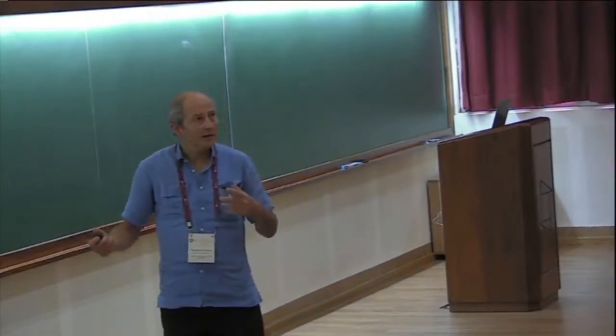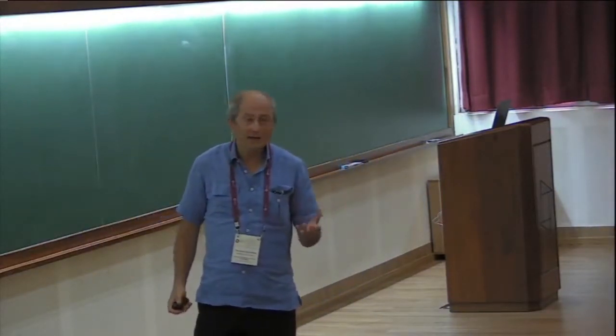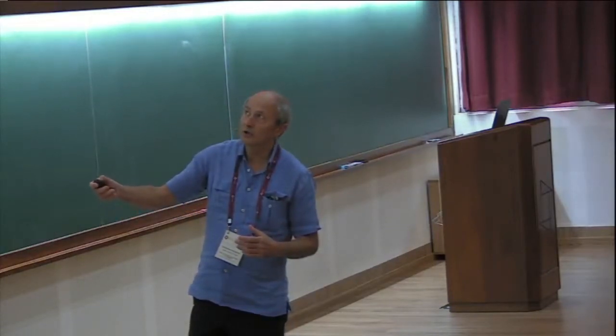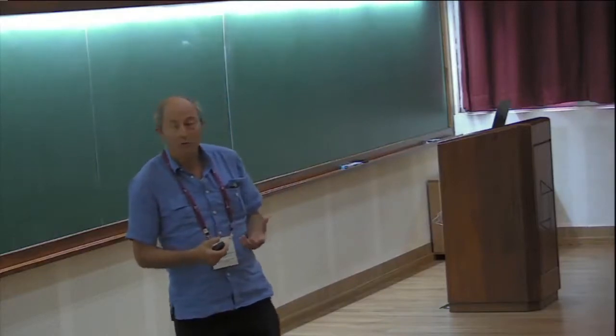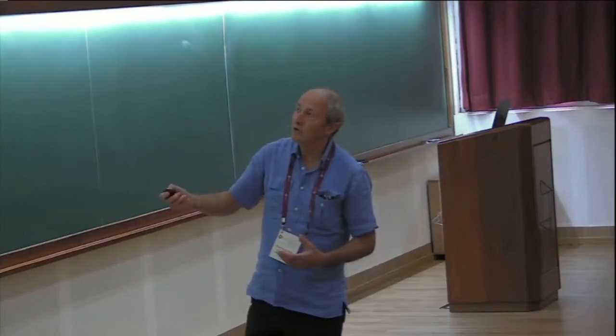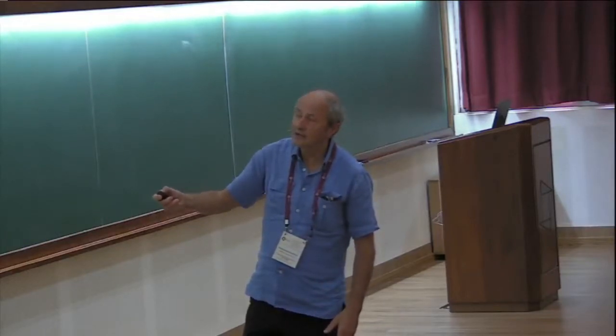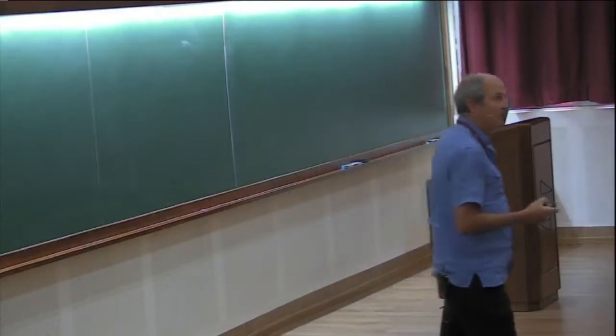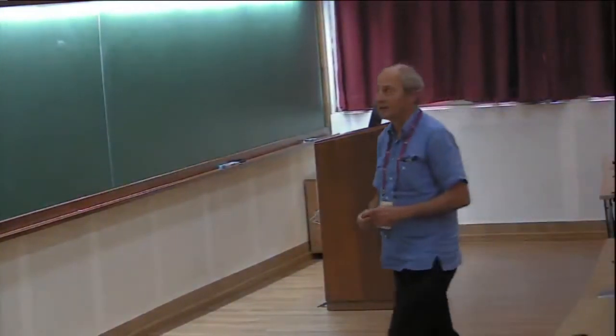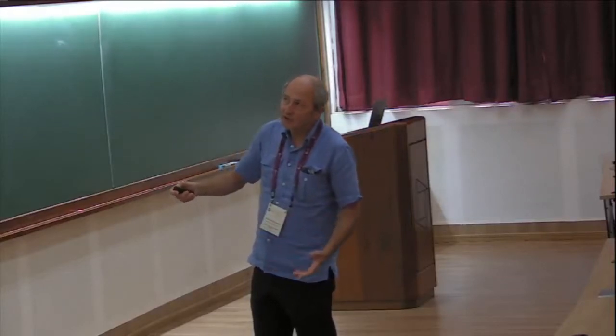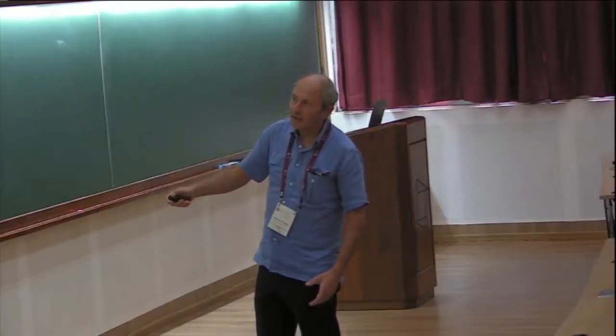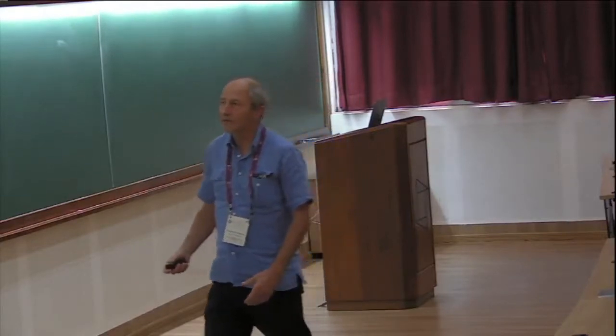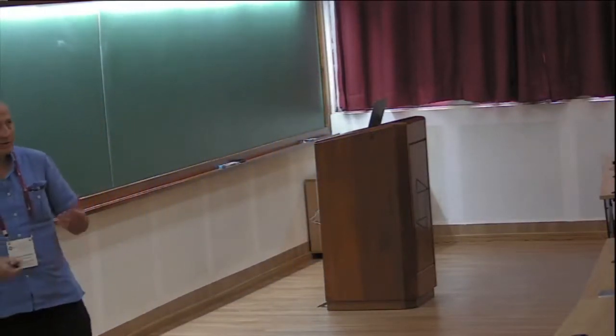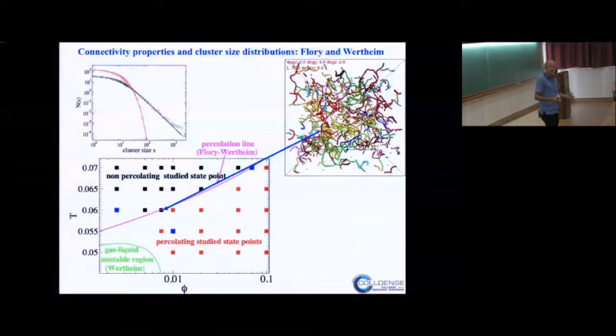We have introduced in the previous lecture the Flory-Stockmayer clusters. And those are the lines that you see shown here, compared with the simulation. You see how good the agreement is, even close to the percolation transition. So they're really a nice description of those clusters, based on the theory that we have discussed, that maximizes the number of different cluster types. So the system is essentially composed of a non-percolating phase, a percolating phase, and then a gas-liquid in the percolating phase. Of course, this line is just a geometric line, because there is a dynamics: the bonds break and reform. It's a system that you can equilibrate. You can easily do simulations down to this low temperature. So this line doesn't really mean much.